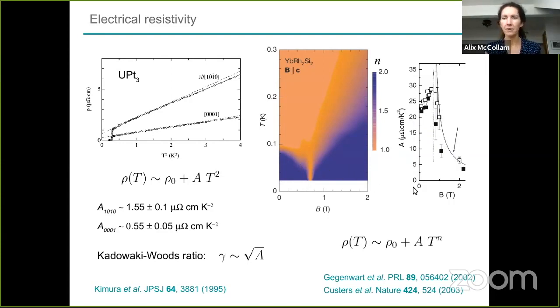At higher field, I've cut this off actually, but if you extend this out to higher field, going out in this direction, then this settles down at a lower number, but still relatively high, still of the same order of the enhancement in uranium platinum 3, and still significantly larger than in a regular metallic system.